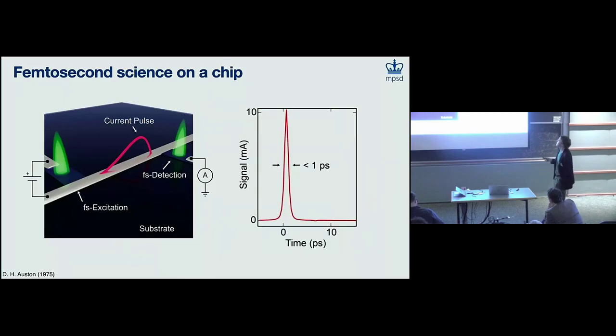So here's the simplest possible ultra-fast circuit that we could make. What we have here is one of these photoconductive switches that's biased against the signal line of a microstrip transmission line. There is a ground line hidden from view, but it's there in the background. And so what happens is if we now photoexcite this switch, it injects a sub-picosecond current pulse into this microstrip transmission line where it begins to propagate.